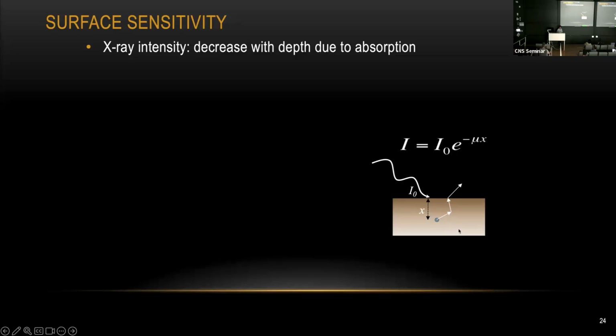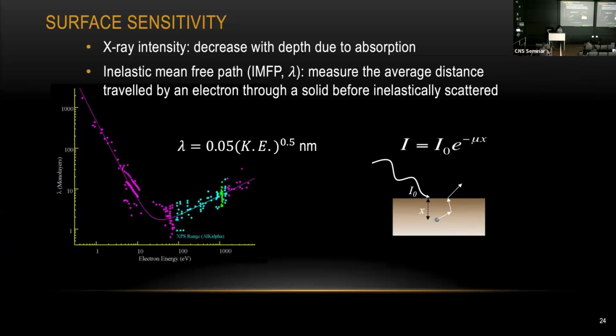The second component that determines your surface sensitivity is your inelastic mean free path. That's pretty much sample dependent, depending on which element you're working on. So for XPS, if you're using an aluminum target, the aluminum metal, to generate X-rays, the region we are detecting is somewhere around this region. That's about 80 eV to about 1,200 eV. That's the range of energy we're going to detect for an XPS measurement.